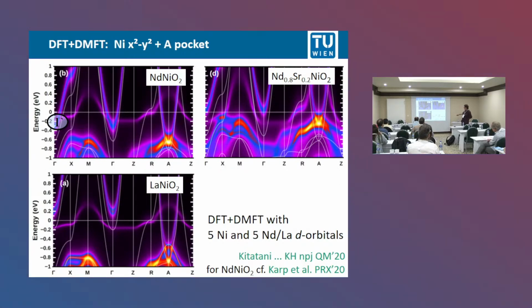But you see still here that's the x²−y² orbital, and you still have an A pocket. The gamma pocket, which was there without correlation, is now shifted above the Fermi level for lanthanum nickelate, but for neodymium nickelate, the gamma band still crosses the Fermi level, and you have a gamma pocket. But if you strontium dope the neodymium compound, also this gamma level shifts up. And because of that, you see here in some compounds, at some dopings, you have the gamma pocket, in others you don't. And because of that, we think it is not relevant for high temperature superconductivity in these systems.